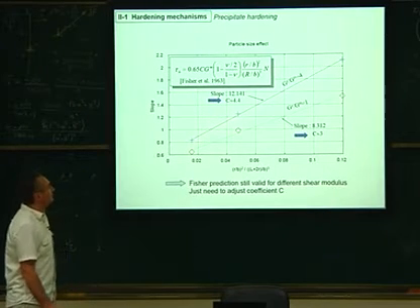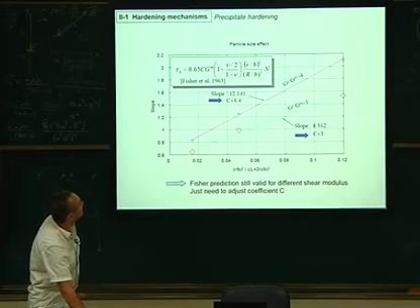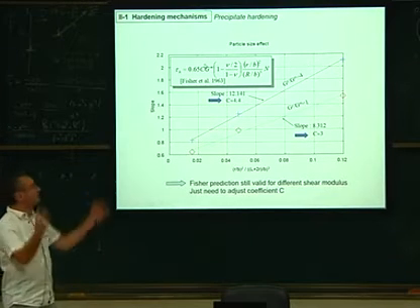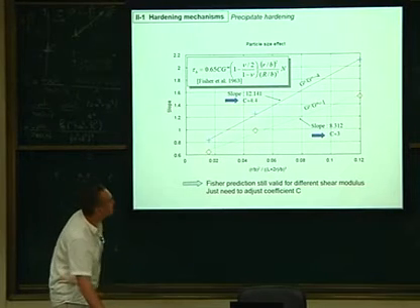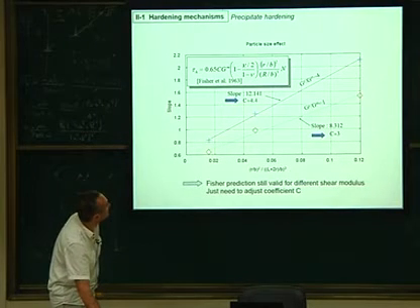And this is the effect of the particle size now. And here there is a nice analytical expression that was given by Fisher, in a case where they didn't take into account the shear modulus, for example. In our case, we took the shear modulus into account, and we found that this relationship still stands.